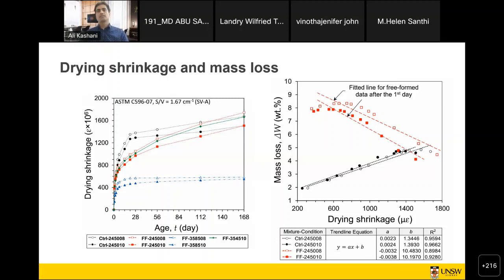But the other factor is that because the samples are underhydrated, there is not enough water in the sample, and that lack of water kind of stops any of those capillary pressures by losing the water over time. As you can see, for example, the control sample just evolves until 28 days and then plateaus. But for free-form samples, you can see it just gradually moving. At the same time it's unhydrated, getting some water from the environment, and also the drying shrinkage is happening. And you can also see that in terms of the mass loss.